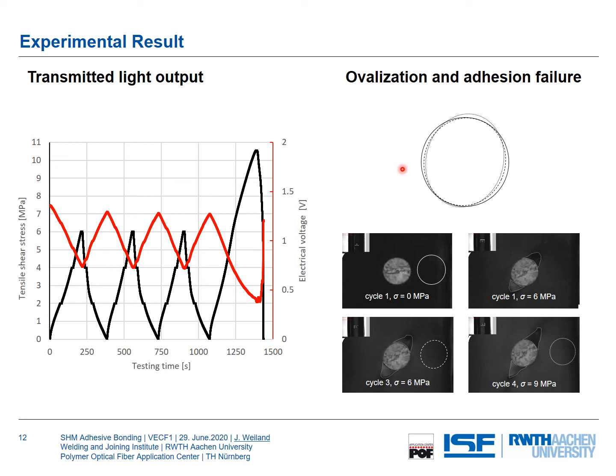The other thing is our second test setup with the high resolution camera. Here you can see 2 different cycles. The cross-sectional shape at the beginning is really a circle, and then, for example, at the first cycle at 6 megapascal, you can see that we have an ovalization, and the same at the third cycle. We also have that ovalization, and that's close to failure. And when we take these shapes and bring them together, which is the picture on the top, you can see we have really a change in the cross-sectional shape of the fiber. And that's the reason why we have the change in transmission of light here.